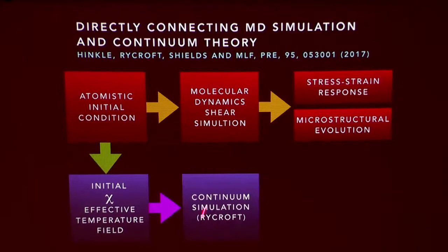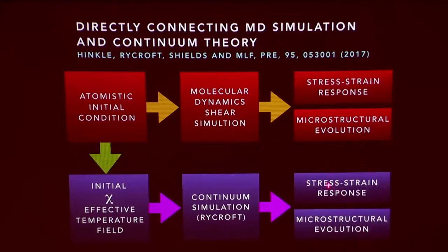Then I can apply the equations on the prior slide, the constitutive law, using a code that was developed by Chris Rycroft. So we do this STZ theory simulation, and that also gives us a stress-strain response and a picture of the microstructural evolution. How did the temperature field evolve? And then I want to compare those two. Does the theory predict the same thing that we see in the molecular dynamics simulation?